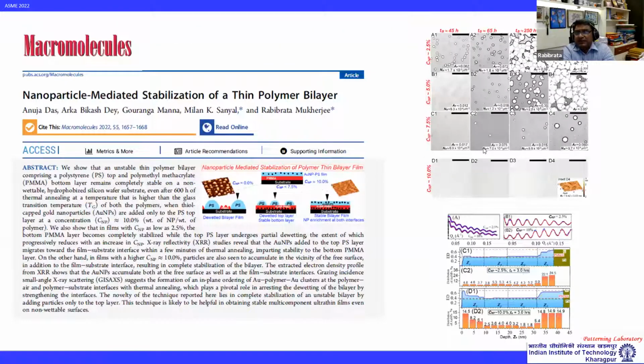We could also stabilize a polymer bilayer, maybe this is one interesting slide, which is a slightly more complicated system. And as I was telling, we use some gold nanoparticles. Microscopically, you see that the film gets stabilized. But we did some XRR measurements in a synchrotron in Japan, and we could actually show that these nanoparticles, because of the entropic effects, migrate to two different interfaces. One is the free surface, and one is the polymer-substrate interface. Because of different reasons, at the free surface it sort of strengthens, and at the polymer-substrate interface it changes the wettability. It even stabilizes a bilayer, a stacked layer of two ultra-thin films, both of which are liable to become unstable.